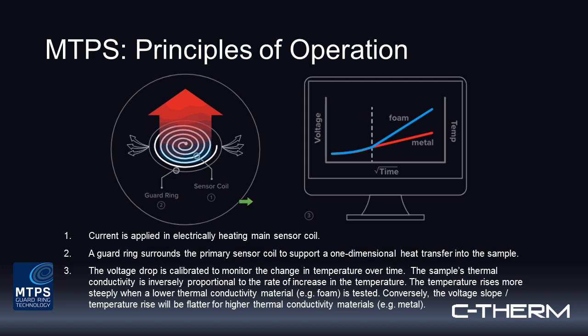The reason for the guard ring is to ensure that we get a one-dimensional heat flow into the sample material. So heat travels in the path of least resistance. We've got an insulative backing material on the other side of the sensor chipset. Both the coil and the guard ring are electrically heated, and this ensures that the measurement sensor, which is the main coil, has a unidirectional pathway into the sample material. So that coil in the middle is both a heater and a detector.